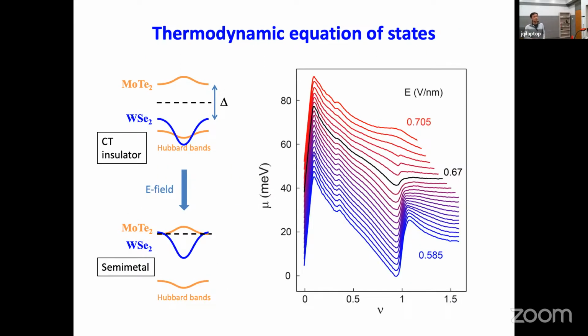So here is the chemical potential as a function of the filling factor. Again, filling factor 1 is one electron per Moiré unit cell. And this is the chemical potential at different electric fields. You can see this is before the system gets to the band edge. When it reaches the band edge, there is a peak here, and then the chemical potential drops. There's a little jump at 1/3, which is a generalized Wigner crystal state, and then another chemical potential jump at 1. Those are the Mott state or the charge transfer insulating state. With increasing electric field, you can also see that the gap at filling factor 1 closes. You can no longer see the chemical potential jump, because with the electric field you invert the band, and it becomes a semi-metal. Okay.